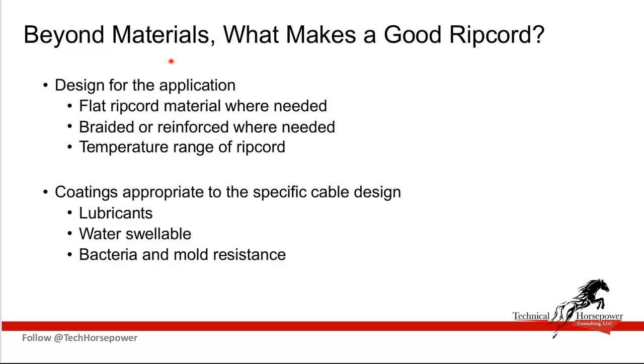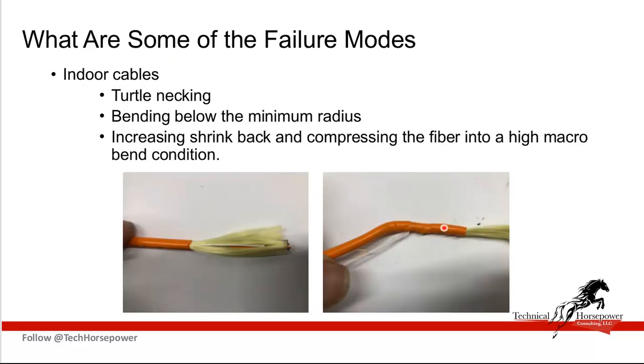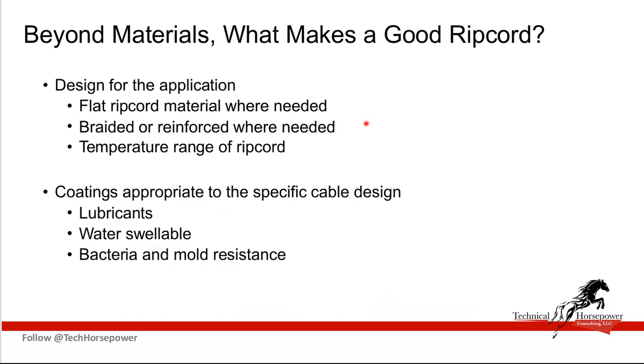Flat ripcord material may be used in certain applications where the jacket is soft. That one you just saw was a good example. The previous slide right here, this is a soft jacket, so a flat or untwisted ripcord will work quite well. But sometimes you have to braid it or reinforce it when you need it for heavier jobs, like cutting through steel armor or the non-metallic armors that are used for termite and rodent-resistant cables, as well as the temperature range. If you use a material that, say, softens at high temperature, it may not work as a ripcord. You may want something that is basically a thermoset material, like an aramid or a fiberglass.